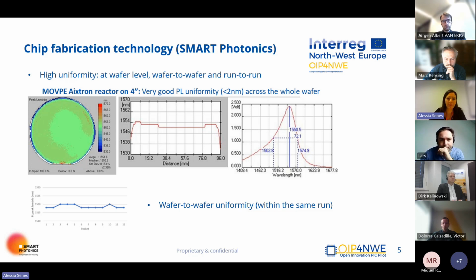And you can see that the PL uniformity is very good, less than 2 nanometers across the whole wafer, centered around the target wavelengths. So this is in-wafer uniformity, and here you see a graph that shows the average PL for each one of the 12 wafers in the same run that are deposited together in the reactor. So this tool really allows high uniformity on wafer and wafer to wafer.